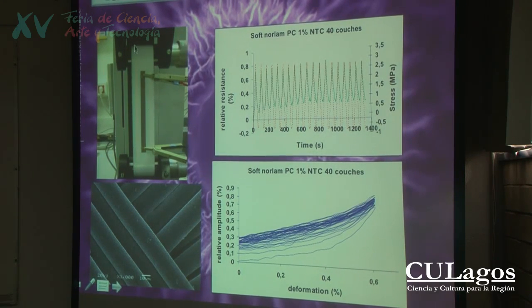Nanocomposite can be also used to monitor the deformation of materials. Here you have the scheme of a sail for boats. It's a textile, and you can put on this textile a very thin layer of nanocomposite that will be able to follow the deformation, as you can see on this graph. So you can follow the deformation, and not only that, you can also follow the damage of the textile, because if you make cycles, you will see that the cycle will not be necessarily reproducible. This means that the sail is going to be damaged upon the application of the strain.